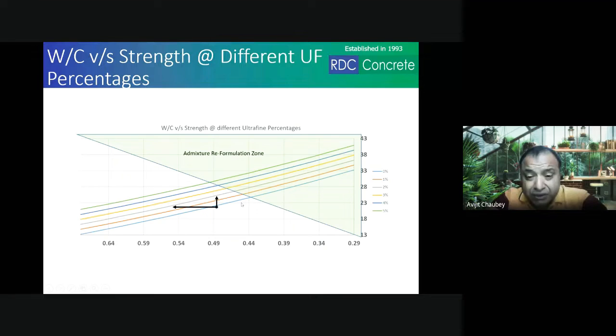Because as you keep on going to a higher and higher level of ultrafine, it starts behaving like a lower water cement ratio concrete. Because even without ultrafine, when you reduce the water cement ratio, you change your admixture. You always change the admixture. You have got mid PC, low PC, high PC. The reason you have got high PC for higher strength is because the water cement ratio is lower. You get higher strengths over there.